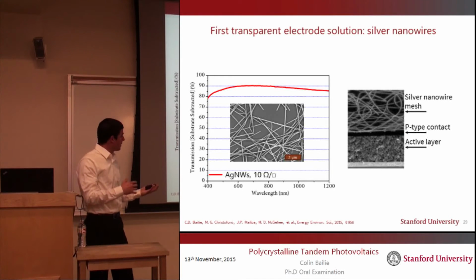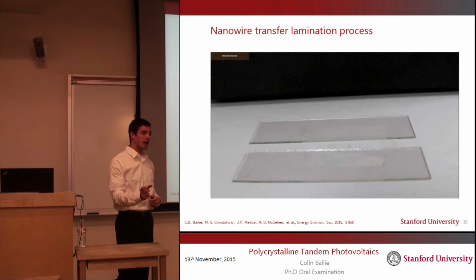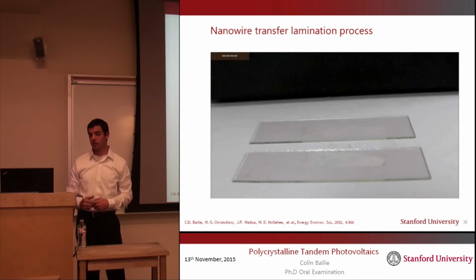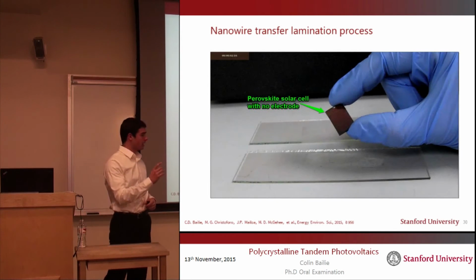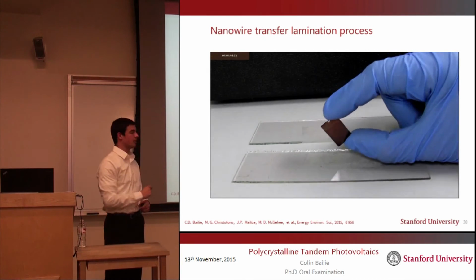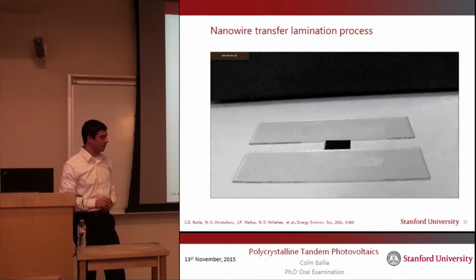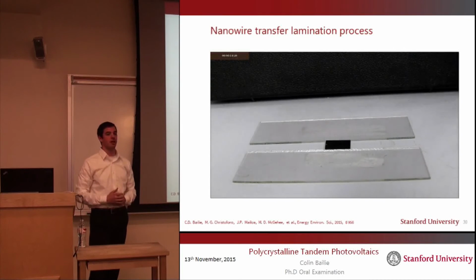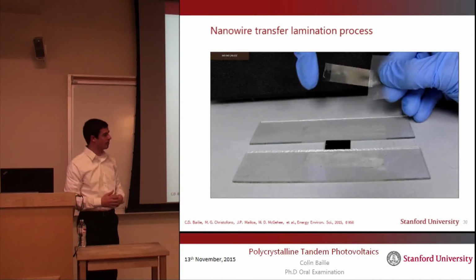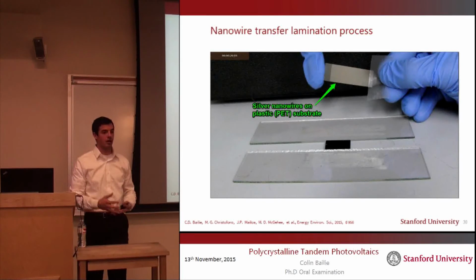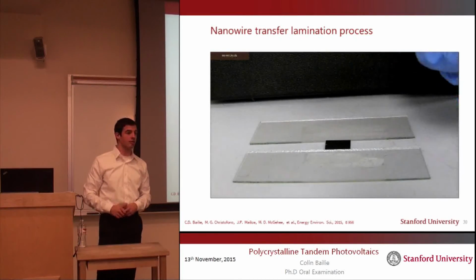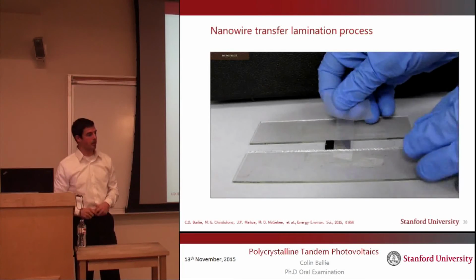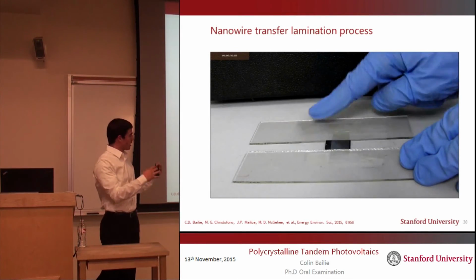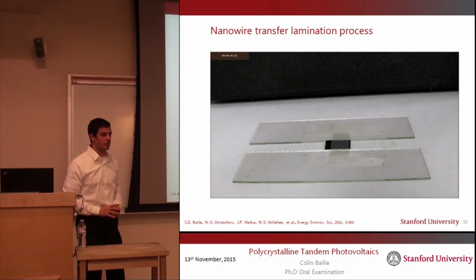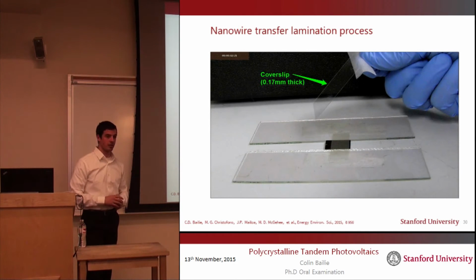And the solution that we came up with in order to make it compatible with the perovskite was to use a transfer lamination process. And so here, instead of spraying the wires directly onto the perovskite solar cell, we instead sprayed them onto a sheet of plastic. The sheet of plastic could be exposed to high temperatures and to the alcohol solvent that we sprayed the nanowires from, meaning that when it was dry and back at room temperature, now we can put it on the perovskite solar cell.